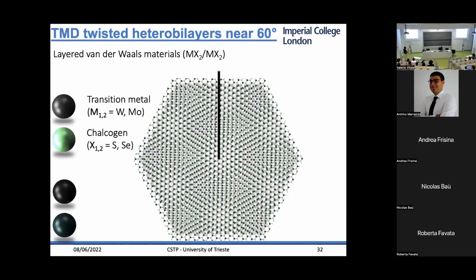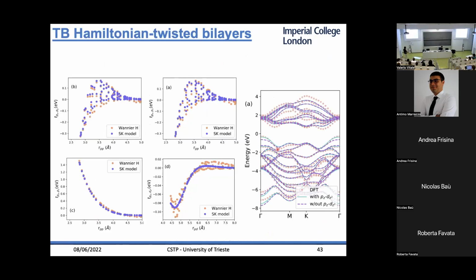Here I have the tight binding versus the other monolayer. This is at the bilayer. But basically, you can already see that even with pz, with dz squared on the gamma states, we don't fully capture it. I know this looks very small, but on the Moiré scale, this is important. Absolutely. But your description ends there, almost just considering the states up to p and d, and that's it, right? Yeah. Then you have to introduce more. Yeah, the basis will be larger.